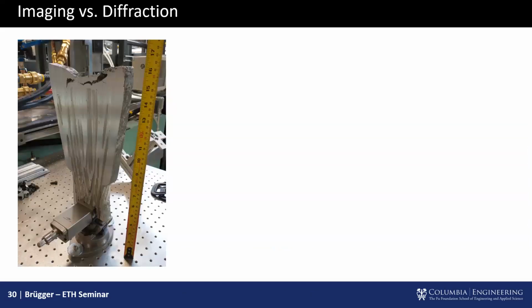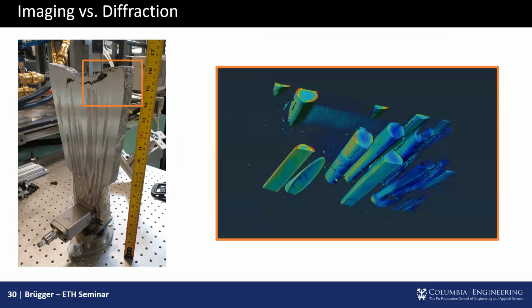So what we did is we said, well, we could take a spelter socket component, so a slice, this is 24 millimeters of that. It's one of those failed sockets, or this is not the one that failed, but it's an immediate neighbor. And we can do radiography and just understand the as found condition, because actually just cutting these with a saw, the stiffness and the strength disparity between the zinc and the steel is so high that you disturb the contact features and the configuration of that sample significantly just by slicing it. So we said, well, we could take a slice and then look inside and see what we find. So we can do tomography, et cetera, and do 3D models of this.